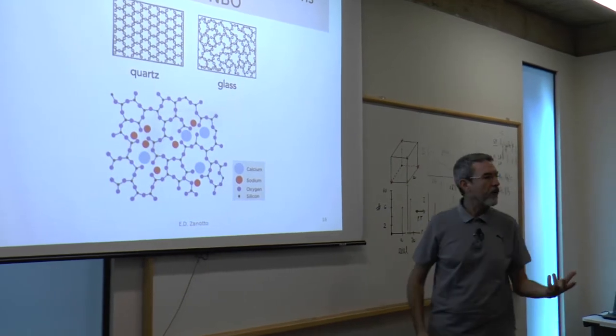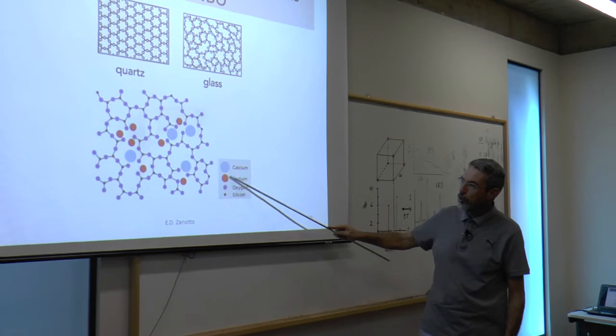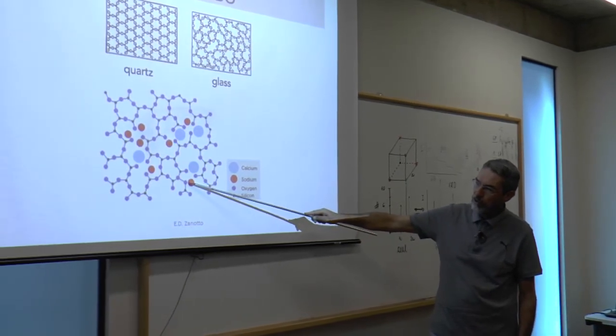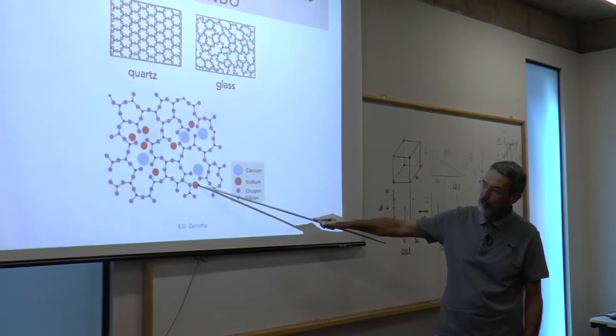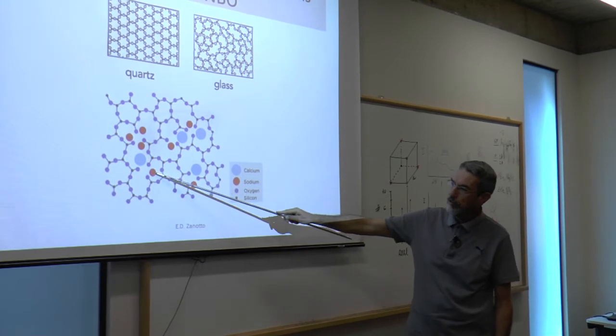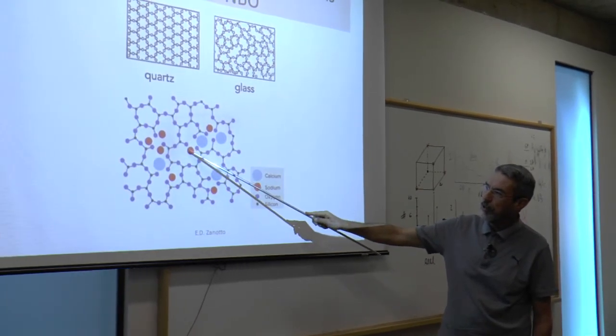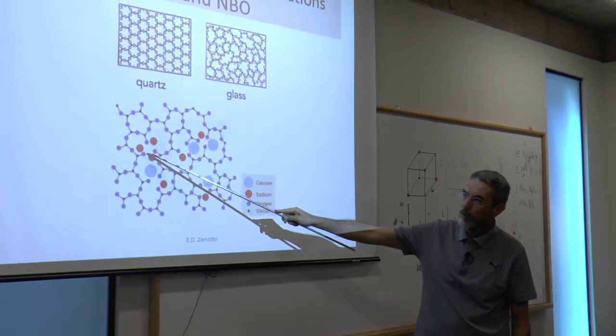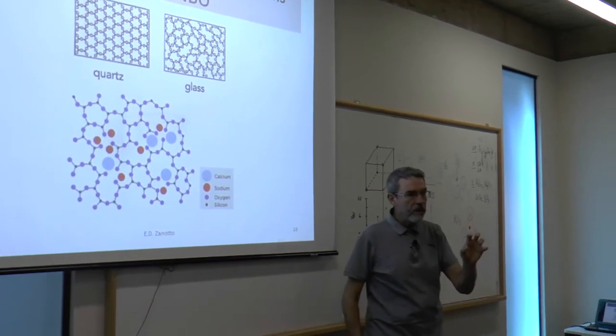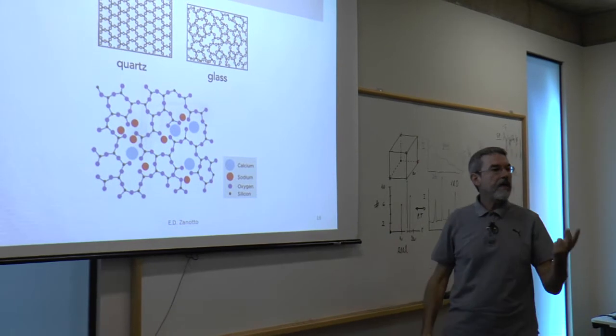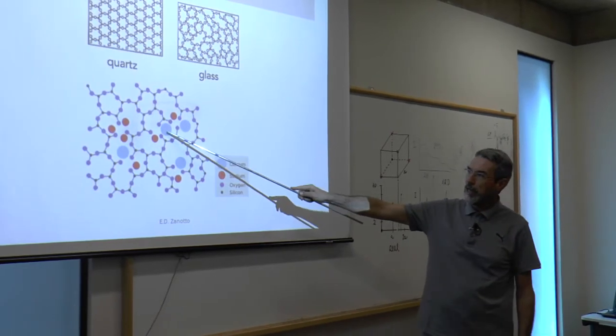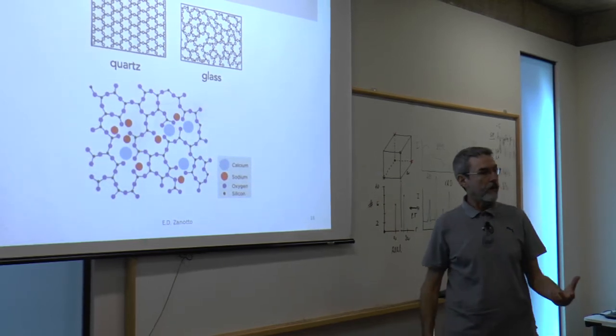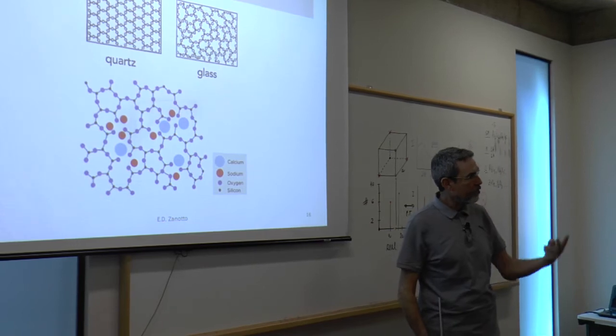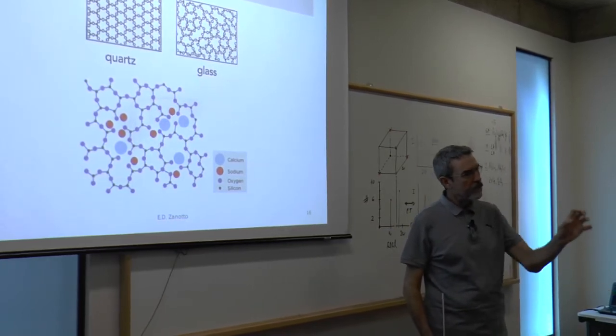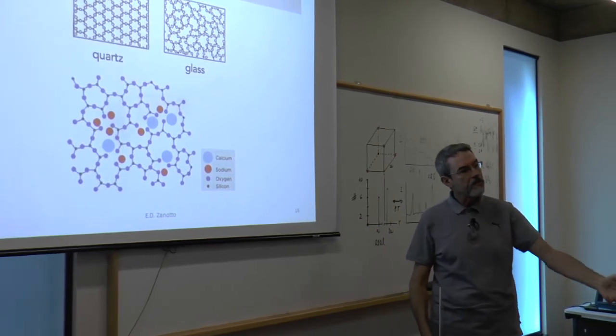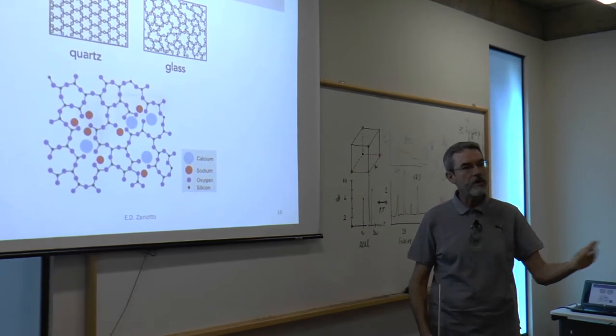But the key point of this drawing is to show that here, the sodium atoms are close to a non-bridging oxygen. This kind of links here. Now with calcium, the valence of calcium is 2. So each calcium has to be close to two non-bridging oxygens. Calcium, or strontium or barium, will be close to 2 non-bridging oxygens. Sodium, lithium, potassium, rubidium, cesium are linked to one non-bridging oxygen.